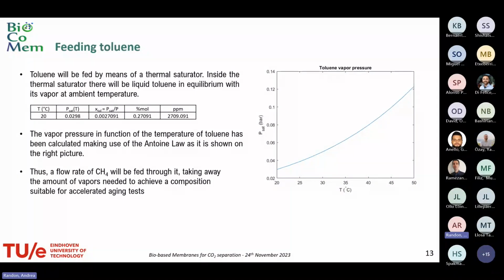At ambient temperature, so 20 degrees C, I calculated the saturation pressure of the vapor through the Antoine law. And we see that the ppm that we obtain in equilibrium, if there is a flow flowing inside, takes an amount of toluene equal to 2,700 ppm. What we need for the aging test is actually 10% of it. So what we do is send in a flow rate of CH4, so methane in the case of biogas upgrading, that will be 10% of the total flow rate. And taking away this amount of vapor, we can achieve the composition which is suitable for the accelerated aging tests.